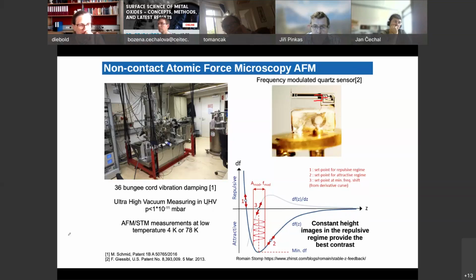Yeah, so in order to do that, what you do is you put the tip in front of the surface, let it change, put it at a set point, so you have a change in resonance frequency, very close. And then you start moving. When the interaction between the tip and the sample changes, you measure the change in resonance frequency. And this is the signal that we give in this image.